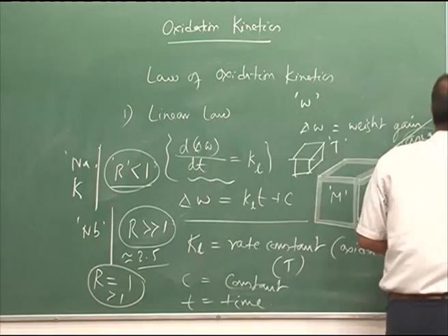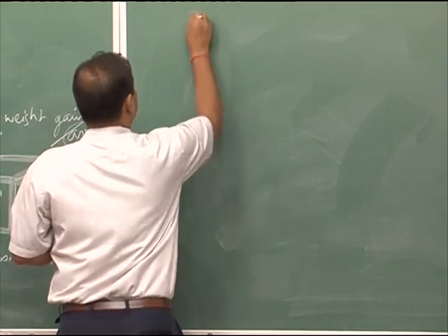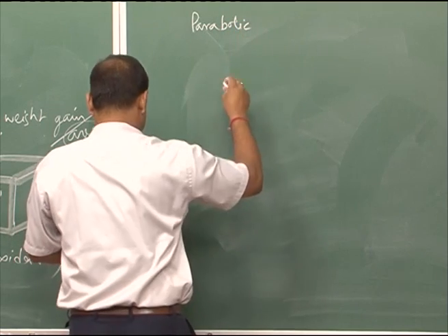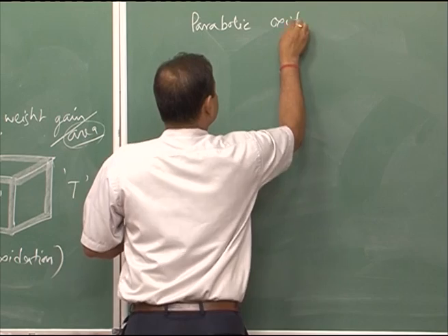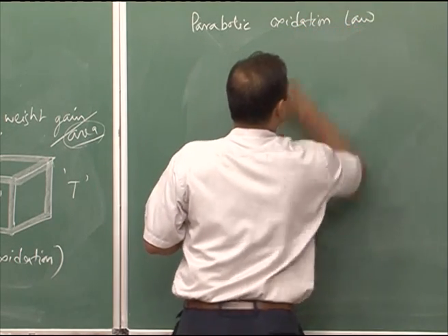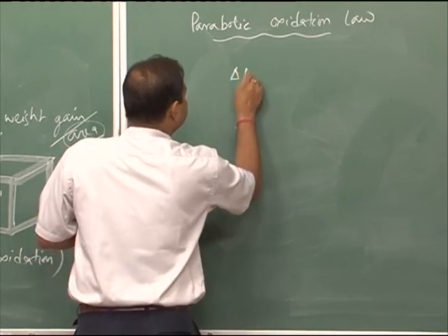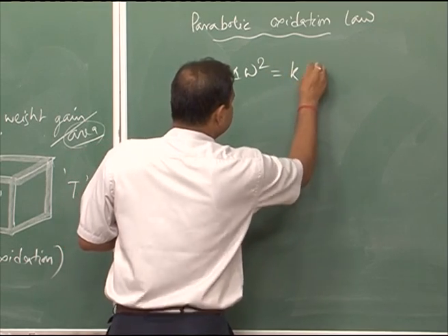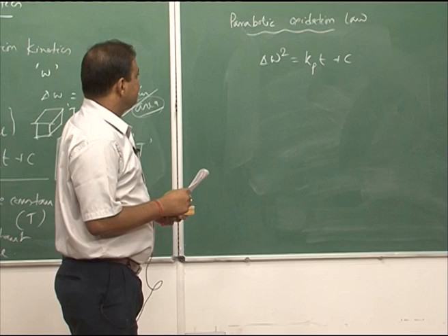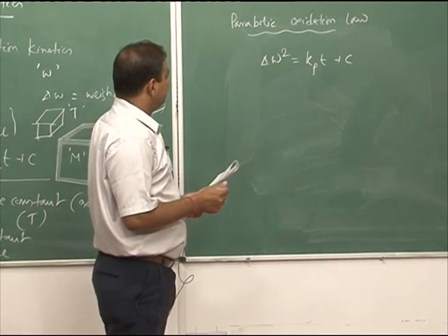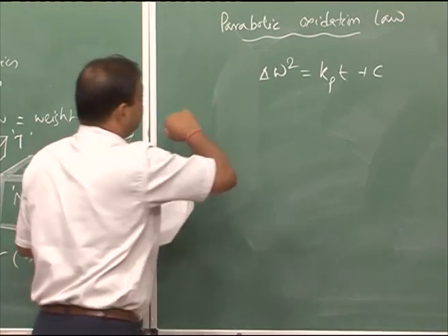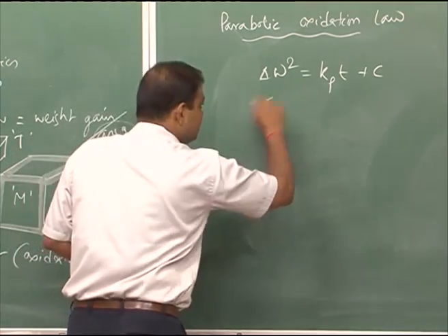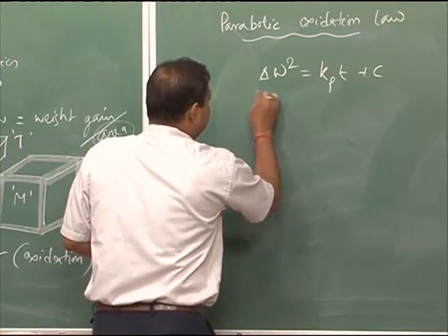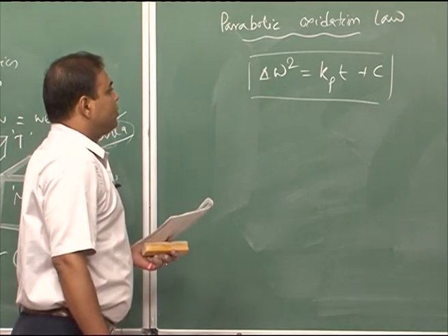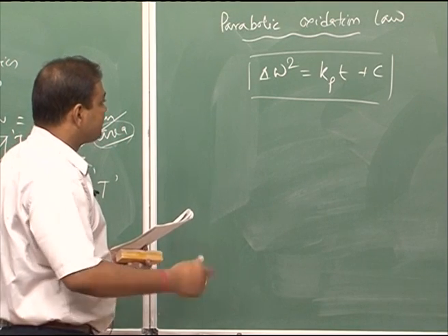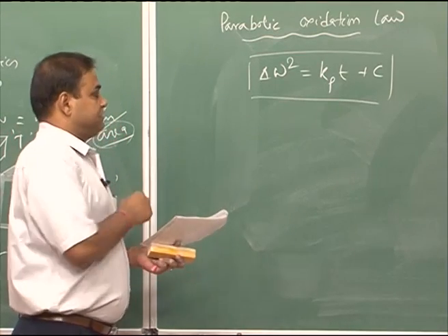Now, let us find out what the other laws are. Then we have the parabolic law. In this process, we see that del W squared equals K_P t plus C. In this case, the square of the change in weight per unit area of the oxide layer would be proportional to time, and that is why it is called the parabolic law. From this we would find that the oxidation rate is gradually decreasing as the time is increasing.